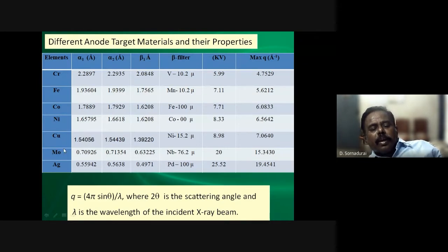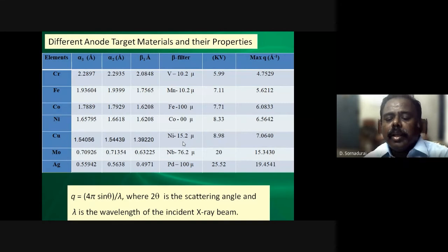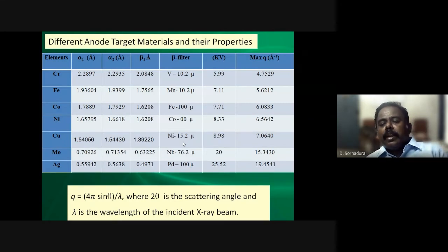Similarly, if you take copper, I have written 1.54056, but we will generally take it as 1.5406. This is the K alpha 1, and then this is the K beta, and the beta filter for this is nickel with 15.2 micron thickness. The critical energy is 8.98 keV, and the maximum Q space. Q space I just put here: Q equals 4 pi sin theta divided by lambda, where 2 theta is the scattering angle and lambda is the wavelength of the incident X-ray.